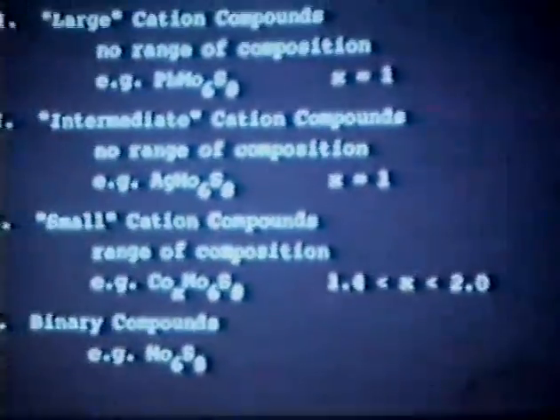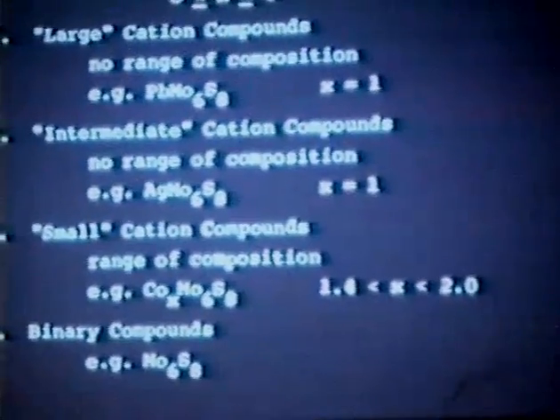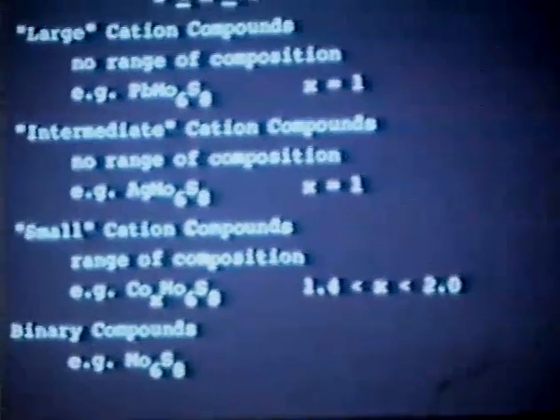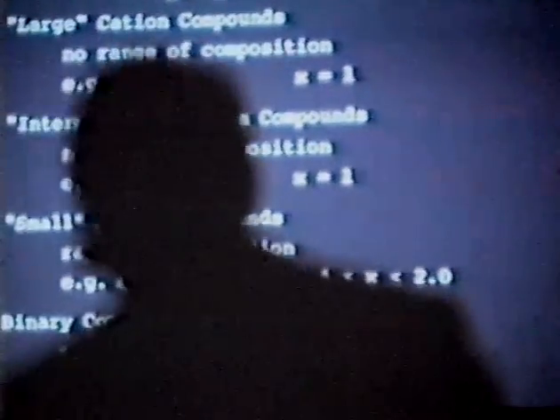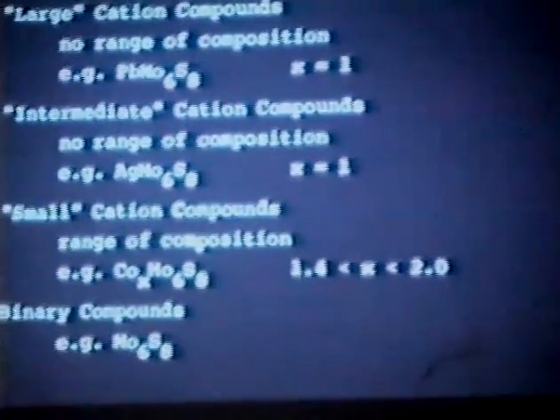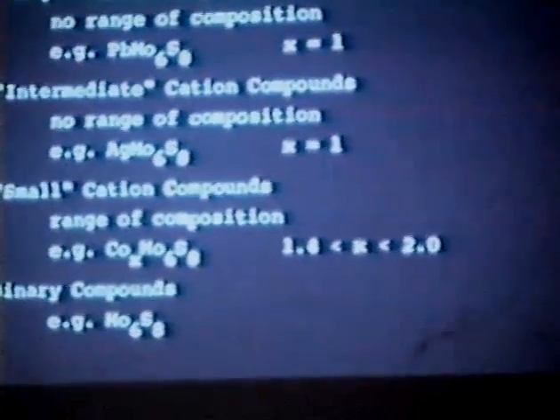Rare earth compounds usually fall in the range of the large cation materials. Their compositions usually have the rare earth in a stoichiometry of 1.2 and then Mo6S8. The rare earth compounds are interesting because you can form some solid solutions with the rare earths, and you can substitute other metals into the structure of the Chevrel phase compound. I'll come to this a little bit later in my talk. This gives you a way of systematically varying the formal molybdenum oxidation state.